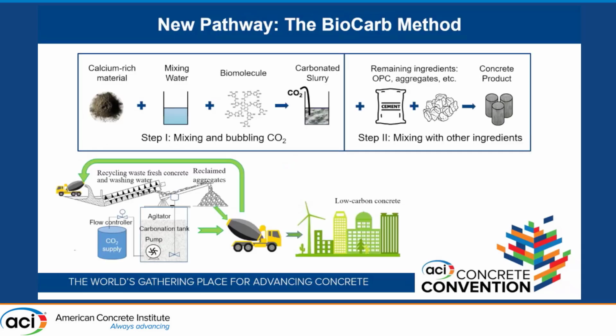So I'm here to introduce a new pathway that I'm calling the BioCarb method. The first innovation here is that we're adding the CO2, what we call pre-carbonation. So we're going even earlier in the process, using the mixing water together with a portion of the cementitious materials to inject the CO2 and absorb it. That way you're able to have more applicability and more efficiency in that CO2 sequestration.